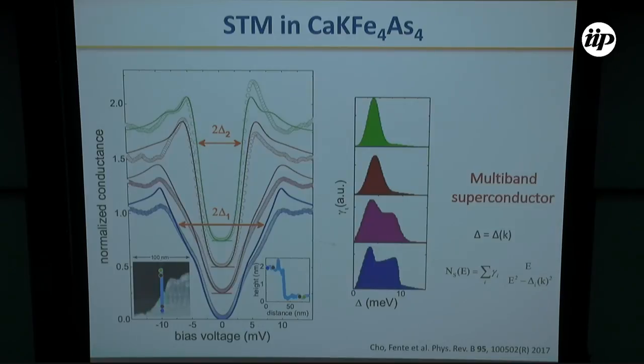When we look at the density of states at low temperatures, we see that it shows the presence of 2 different superconducting gaps. It can also be observed in the gap distribution shown on the right. So we always see two peaks in the gap distribution, around 3 millielectron volts and 7 millielectron volts, although the relative weight between the two gaps changes a bit with the position.